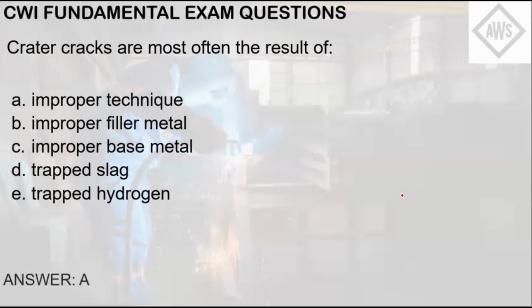So the answer here is letter A. So the improper technique of the welder most often results with crater cracks. For the choices here, that's why they're not the correct answers: filler metals and base metal do not cause rapid cooling. It depends upon the heat input. Trapped slag mainly causes slag inclusion, and trapped hydrogen can cause embrittlement and can eventually lead to cracking as well, but not crater cracks since it does not lead to shrinkage stresses, unlike the improper technique or improper termination that I've just mentioned earlier. So the answer here is letter A.